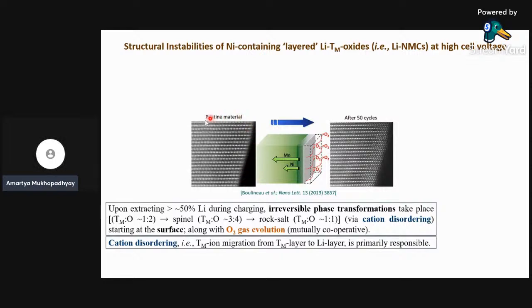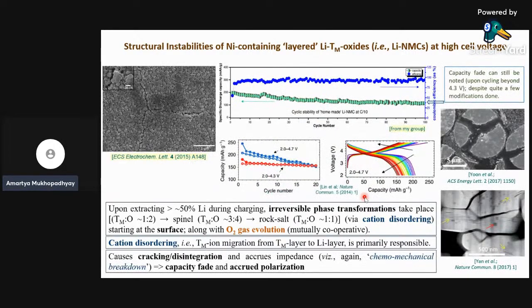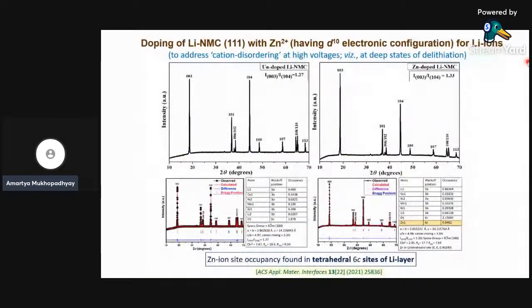Now, if you look at this, to start with, the entire material looks nice and layered. However, after 50 cycles, the surface looks very different, and this is the formation of the rock salt structure at the surface. This leads to fade in the capacity. As you can see here, if one goes to higher potential as compared to here, the fade in capacity is quite noticeable. And such phase transformation also leads to cracking and delamination of the active material from the current collector. So this has to be addressed.